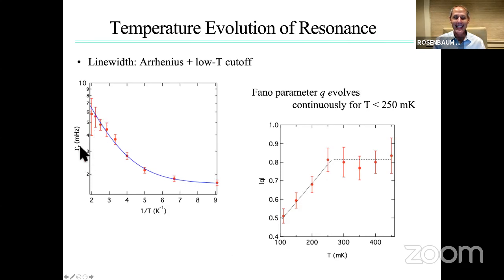The line width gamma in the Fano form is basically Arrhenius. Okay, so I'm just having a thermal excitation process. And then you can see what the Fano parameter Q is doing. At low temperatures, it's some mix of these different pathways. As I raise temperature, I'm exciting more of these clusters. I'm flipping antiferromagnetic bonds to ferromagnetic bonds. The clusters start revealing themselves to each other and start interacting. And I wind up at one limit of Q. Q goes from 1 to -1.